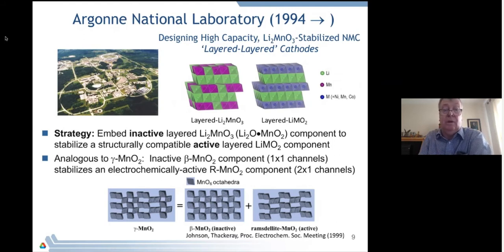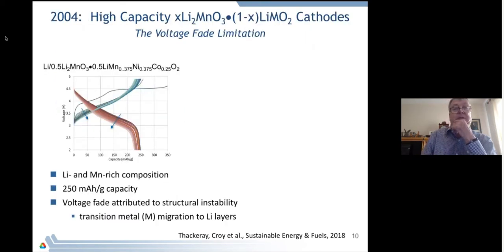The strategy there was to, again, embed Li2MnO3 as the inactive component and to stabilize the structurally compatible active layered NMC component. And this idea is analogous to the structure and electrochemical operation of gamma MnO2, which consists of two components, an inactive beta MnO2 component, which is structurally integrated with an electrochemically active ramsdellite MnO2 component. These layered materials, what I call Li2MnO3.LiMO2, worked in a certain sense quite well.